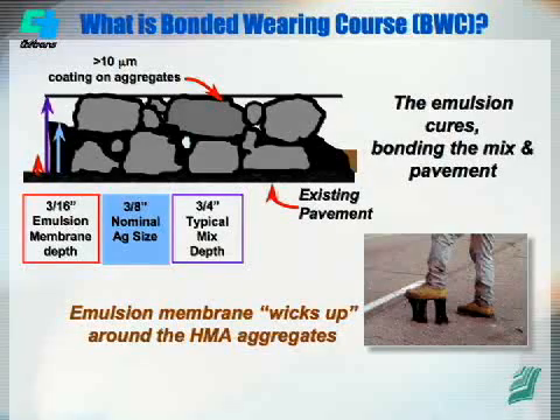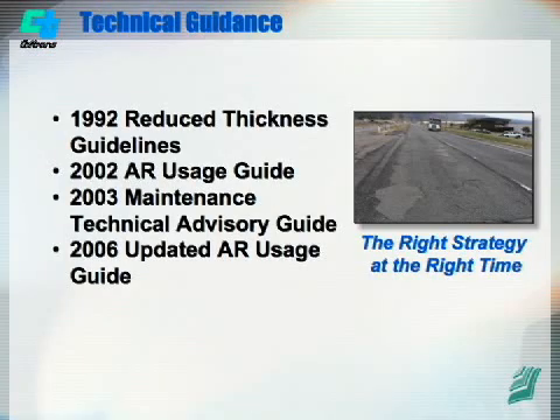And recently, as I mentioned, we have specifications for bonded wearing course, open-graded and gap-graded. This type of strategy uses a heavy emulsion membrane on the surface, and you add to it a very thin layer, about 3/4 of an inch of a surfacing. And we have built several projects with this strategy here.